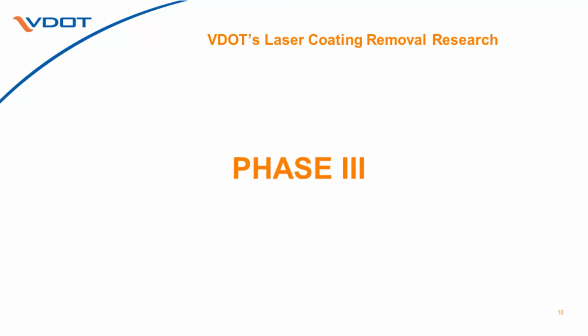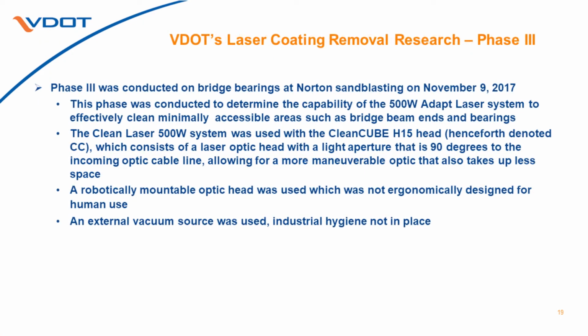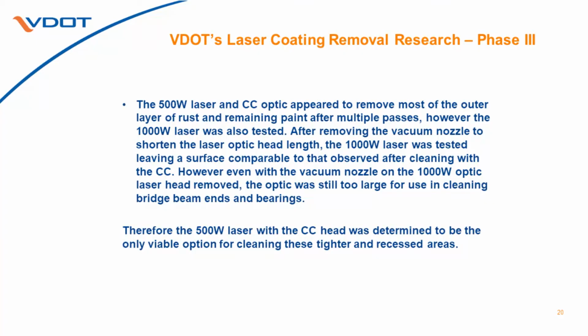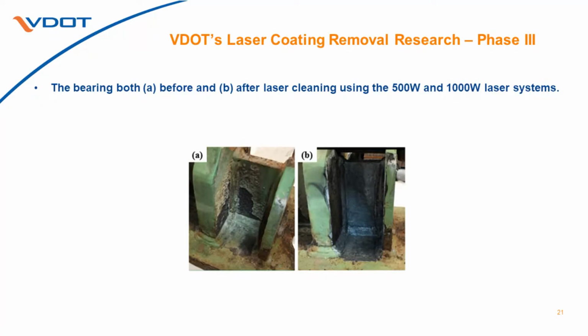Phase three, we decided to take some bearings again to the same private facility and to see if we could improve our production on the bearings in some of the areas that were hard to get to. So we used a 500-watt laser as opposed to a 1,000-watt laser, which had a smaller head. In doing that, we determined that the 500-watt laser was really the only viable option for cleaning around bearings and in these tight spaces. That's just some photos of the bearings that we cleaned in phase three.